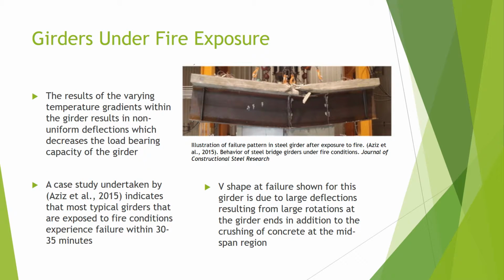The varying temperature gradients within the girder result in non-uniform deflections, which decreases the load-bearing capacity of the girder. A case study indicates that most typical girders that are exposed to fire conditions experience failure within the first 30 to 35 minutes.